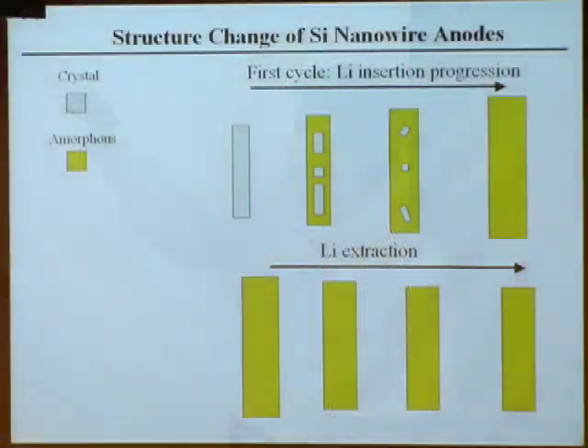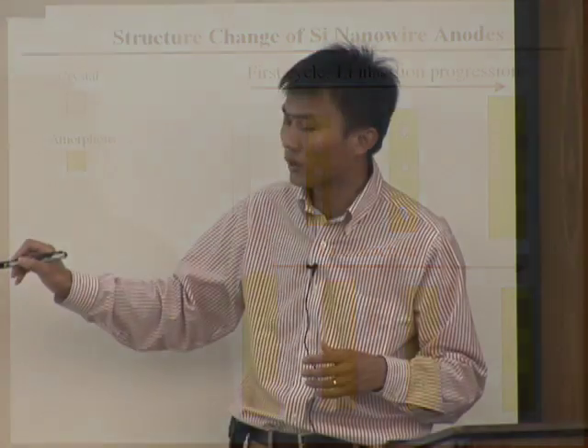Now if you take out lithium, you start with this amorphous silicon with lithium in it. Now you take out lithium, and this silicon nanowire shrinks a little bit, but not completely back to the original crystalline structure. This is still quite big. If you do multiple cycles, this size can increase a little bit more, maybe approaching this size after multiple cycles. So the key information I would like you to get is that this crystalline phase is involved, and this amorphous phase is involved. Now you go back and look at our potential curve.